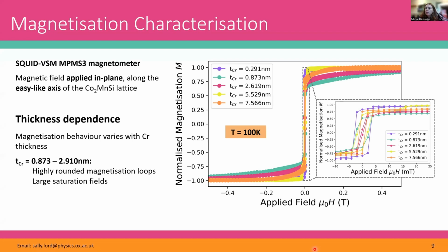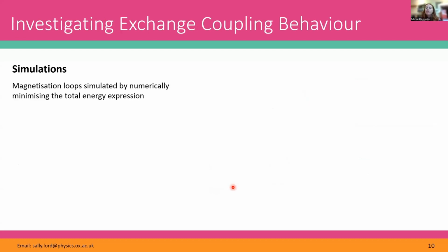And I think what is clear is that the thickness of the chromium really affects the magnetization behavior. So you can see that for these pink and green loops, which correspond to about 0.873 and 2.619 nanometers of chromium, you have this highly rounded magnetization behavior that's not seen for some of the other chromium thicknesses. And we've also observed large saturation fields of the order of half a Tesla, which is about 10 times greater than the saturation field that's measured for a single film of cobalt manganese silicon of the same thickness. So clearly, varying the chromium thickness is having effects on the coupling behavior of the trilayers, but how do we quantify this? In order to quantify this exchange coupling behavior, we moved to simulations.